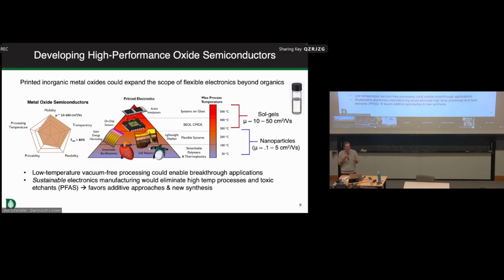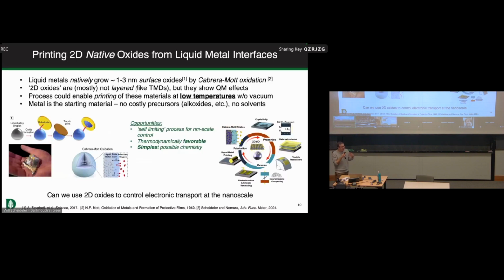It also means that you cannot use the same range of substrates and you can't have the same functionality integrated, for example, in 3 dimensions with silicon microelectronics. So there's a lot of trade-offs that we make when we use higher temperature materials. So the really interesting processing method or synthetic method that we've been working on, the idea came out of a study published from a group in Australia in 2017 in Science, and they discovered that the native oxide that grows on molten liquid metals can be one thing. It can be highly continuous, so you can essentially transfer it using van der Waals forces to a target substrate.